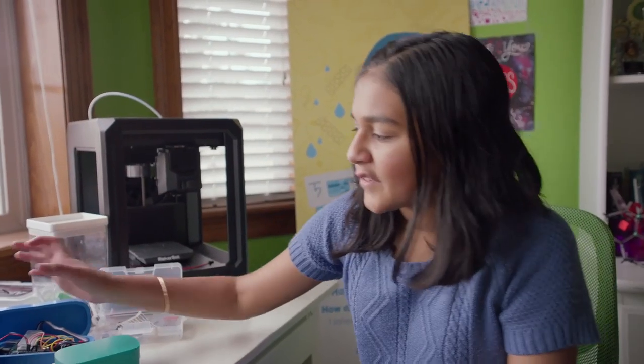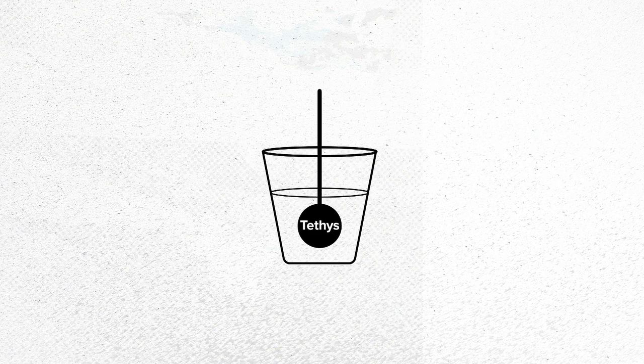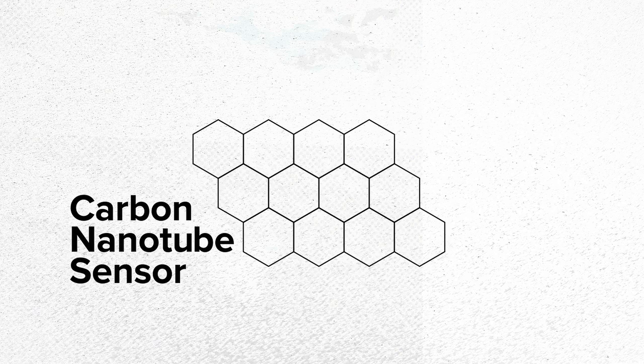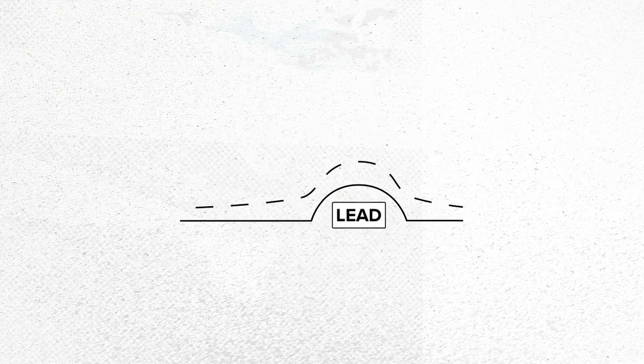So these are all my versions of Tethys. This is the first one — you dip this cartridge into the water you want to test, and the carbon nanotube sensor measures the lead in the water. The carbon nanotube sensor is pretty much like this, and I embedded it with chloride ions, which are the green ones over here. The lead in the water sticks to the chloride ions and forms almost like speed bumps, so the more resistance there is in the circuit, that means there's more lead.